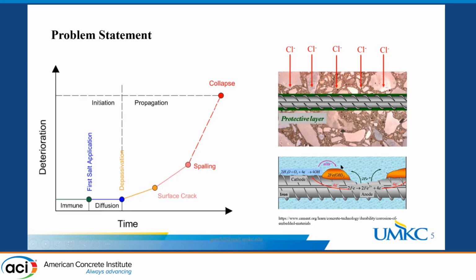Probably most of you know that corrosion product is an expansive material, with a volume 2 to 6 times larger than the original consumed material. So over time the corrosion product at the steel reinforcement generates tensile stress. As soon as the tensile stress of the corrosion product is higher than the concrete strength, corrosion cracks will appear. We can see this in the deterioration model as well: the initial immune state, diffusion, chloride penetration, and cracking. Once cracking happens, because there is a direct source of oxygen and water, the corrosion is accelerated very significantly.